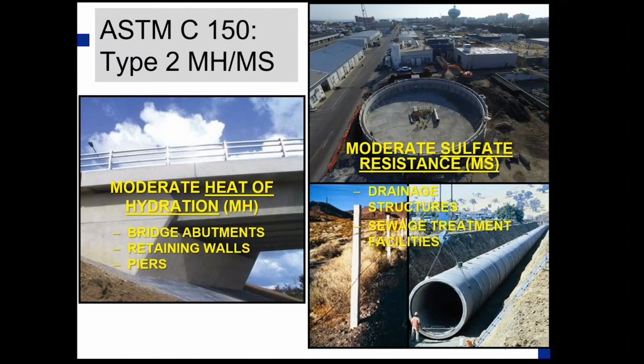But also you might see a type 2 specified on a project where you need moderate sulfate resistance. So that could be any kind of drainage structure, sewage treatment facilities, wastewater treatment plants, something of that nature might call for a moderate sulfate cement as well. And when we're talking about type 2, typically we start to think about that C3A. It's a tricalcium aluminate phase, and the content of that C3A is the main control factor with type 2, and it's limited to 8% maximum. So we'll kind of unpack that when we get to the mill test section.